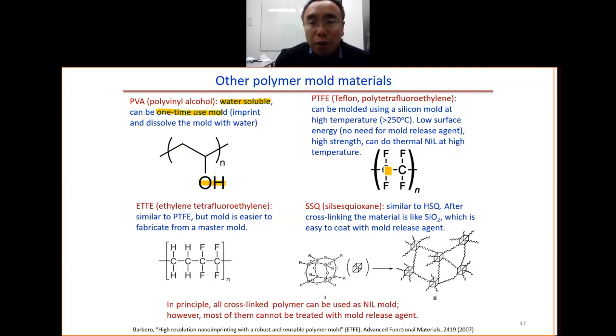This one is Teflon. We have talked about this. This one obviously gives you very low surface energy and is also very stable at high temperature. It is stable at more than 250 degrees, so it is good for the thermal imprint and also for the UV imprint. But the problem is that it is very difficult to make the mold in this material by the hot embossing process. I have done it once. After you press the silicon mold onto the Teflon, then you cool down, the sheet got bent and deformed, not good.